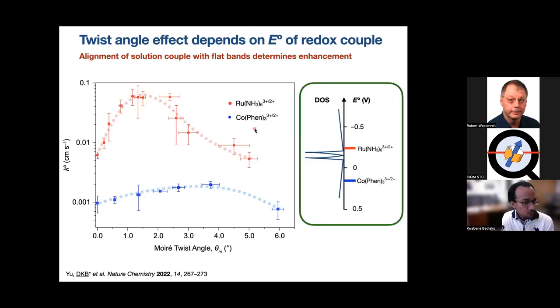But that's just for one type of molecule that we measure. If we look at another example, this cobalt molecule, and we study the interfacial charge transfer with that, we find instead that the effect of the twist angle is strongly quenched. So not only do we see minimal enhancement, but actually, if you looked at this with the mother's loving eye, you would say that the maximum, small and subtle as it is, is at a much higher angle.